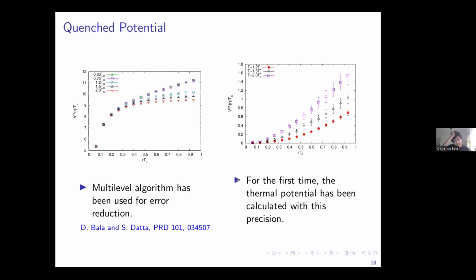And here is the first time I performed the calculation of the potential with this kind of precision. Here is the real part I show, and here is the imaginary part I show. We can see that this real part shows confined behavior, and now as we increase the temperature, it shows screening behavior. And the imaginary part is, on the other hand, increasing with both distance and temperature. It is pure gluodynamics, and therefore you can use a multi-level algorithm to reduce the error.